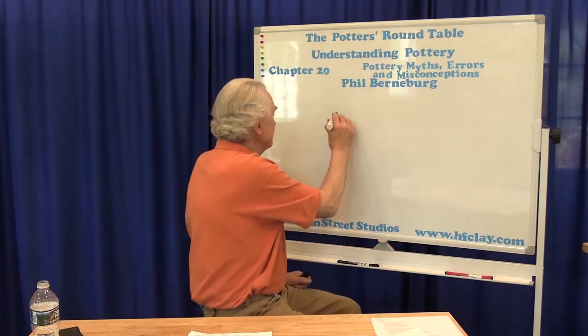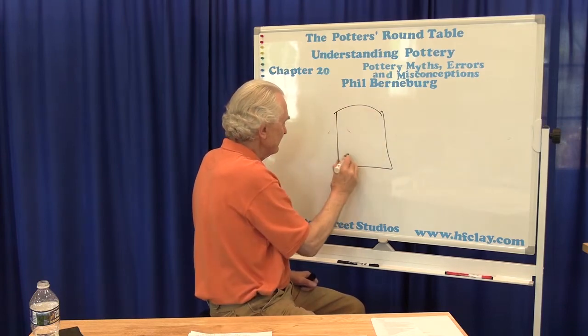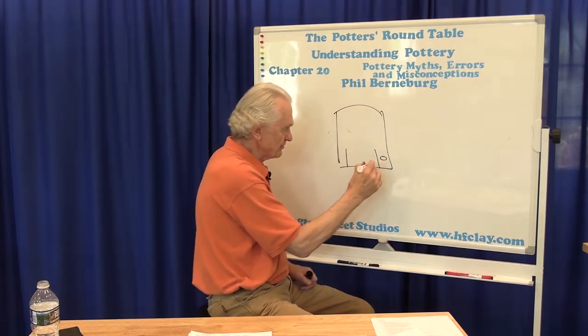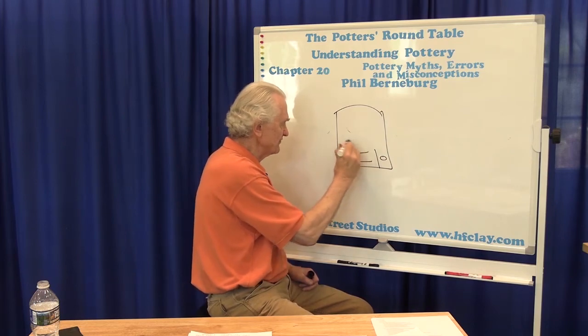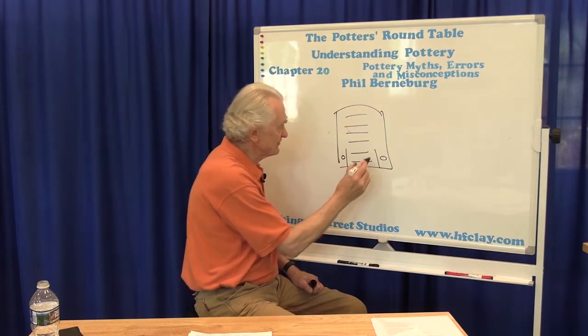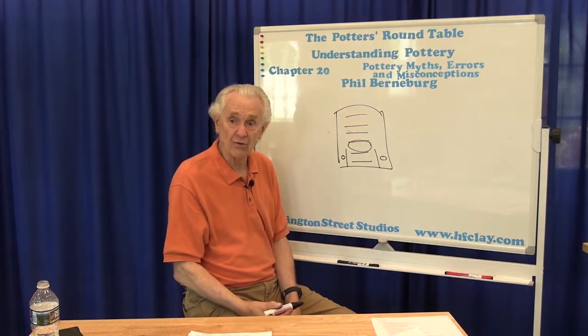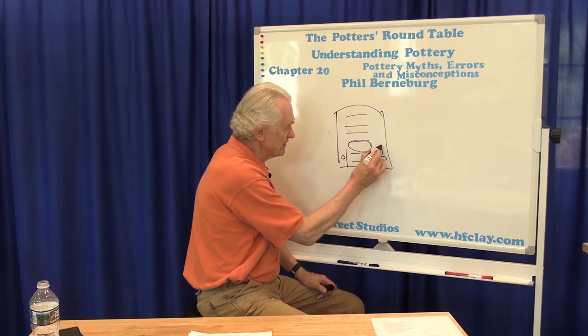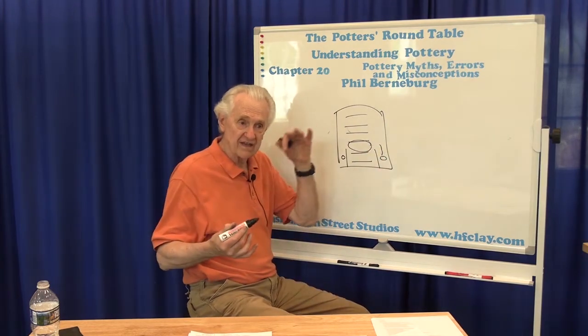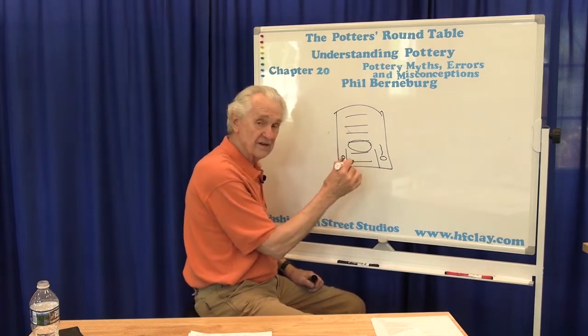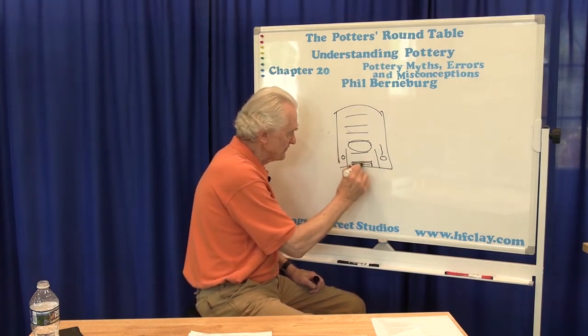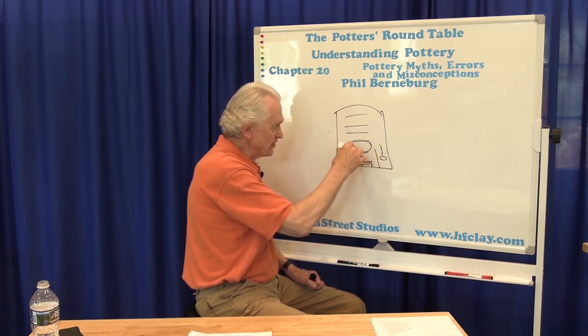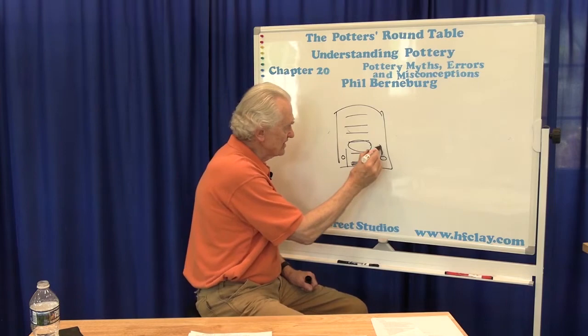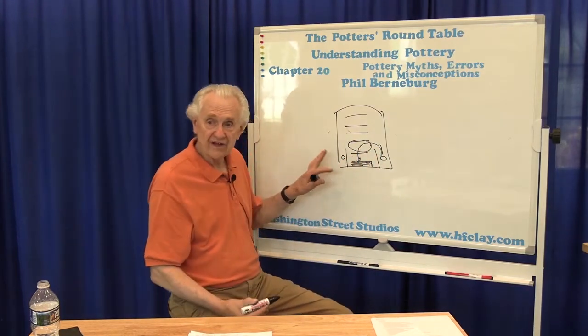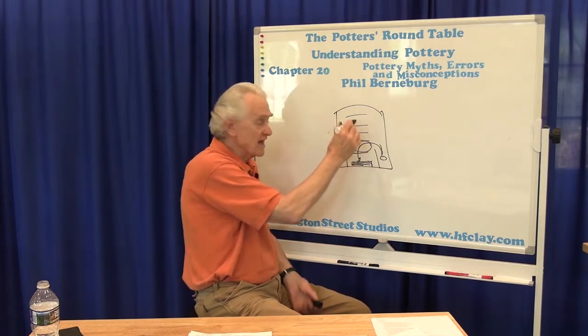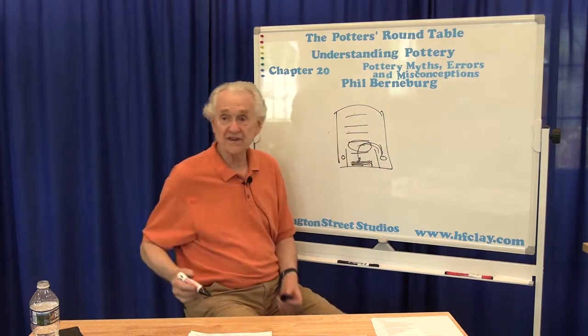As a matter of fact, if you do a little diagram of a gas kiln, let's say these are the bag walls. I've got a burner blowing in here and a burner blowing in here, and this is my shelf stack. It's actually fairly common in a gas kiln to have the region just above the top of the bag wall be the hottest, because the flame is coming up and it's going to make its shortest path to the exit. So if on the other end of this kiln there's a hole leading to the chimney, the flame is going to come up and go over the bag wall and go as fast as it can toward the exit, so it's flowing like that. So it's very common in a lot of gas kilns for the hottest area to be neither the top nor the bottom, but right over the top of the bag wall.